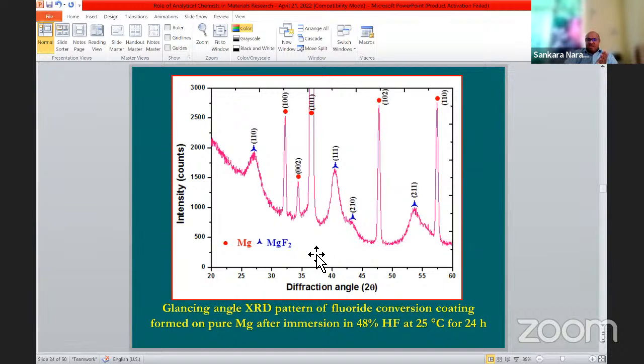So once the surface is covered by a magnesium fluoride layer, there won't be any further dissolution of magnesium metal in the acid. So there won't be any chance of developing a thickness of the film. So the fluoride conversion coating is very thin, less than 1 micron most of the time.